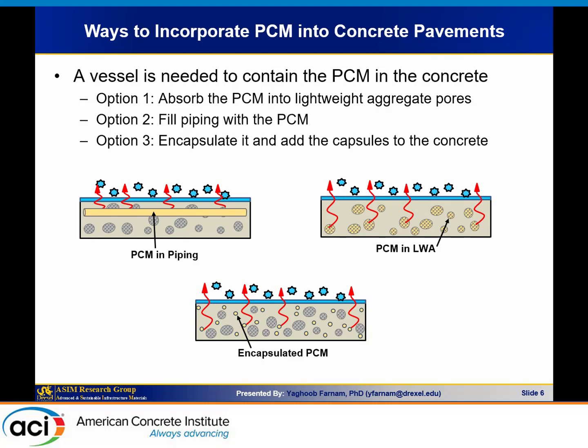The other idea is using porous lightweight aggregate. In this case, you use the porous media as reservoirs for these phase change materials. It's the idea of internal curing that we have been using for a long time. So we soak this lightweight aggregate inside PCM, and then we could store the PCM inside that. The third idea is just using capsules. These are capsules that are available in the market, and you could mix the capsules with your concrete and get benefits from these phase change materials.